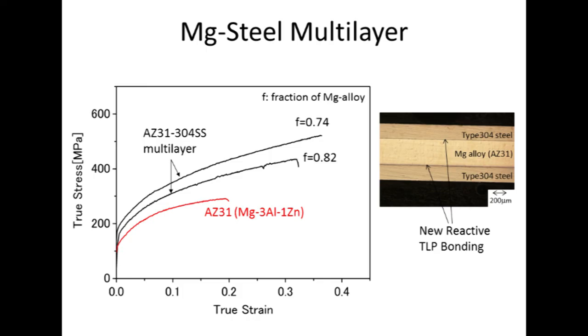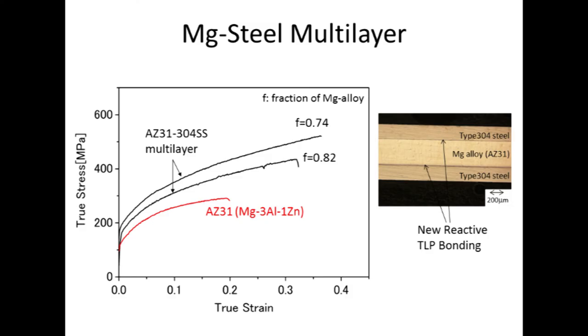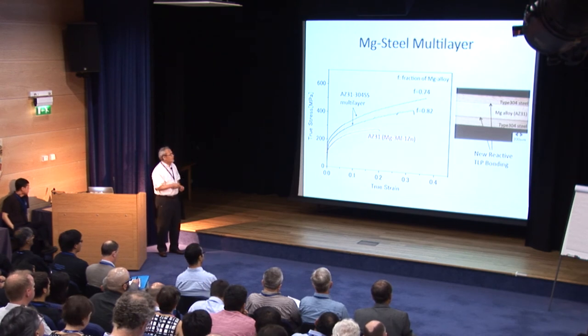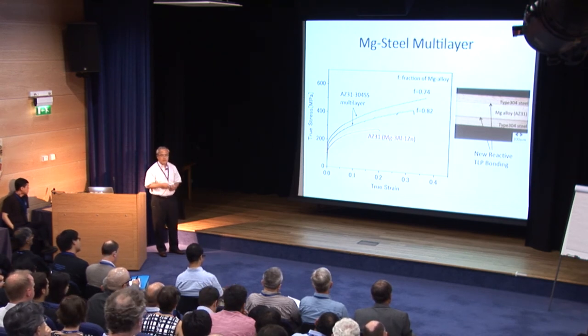Here is an example of a magnesium-steel multi-layer. We developed a good bonding process to join magnesium and steel and fabricated a three-layer magnesium-steel multi-layer. Magnesium is commercially the lightest available metal. The problem is ductility: because of its HCP structure, elongation is up to 20% or even less. But by employing a multi-layer structure, we can increase the ductility of magnesium without any fracture, up to 35% to 40%. Strength is also increased due to the steel layers.